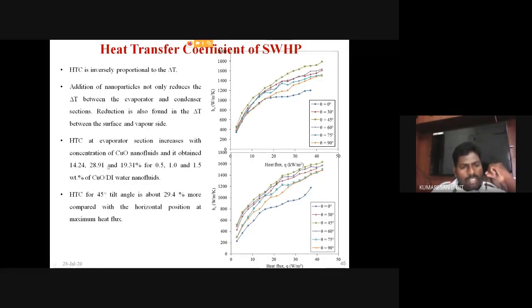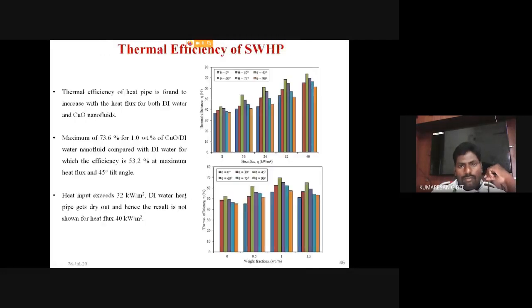You see here that the HTC value is maximum when we are adding the nanoparticles at 1 weight percentage. And in another study, by tilting, that means by varying the orientation of the heat pipe, the HTC value attained a maximum increment of 29.4% at a 45-degree tilt angle. Okay. Then finally, the thermal efficiency of the sintered wick heat pipe.